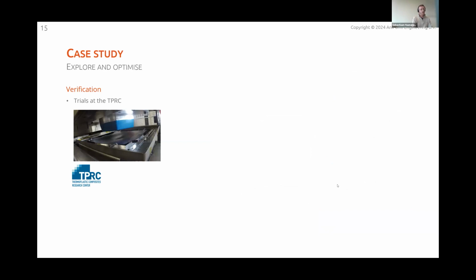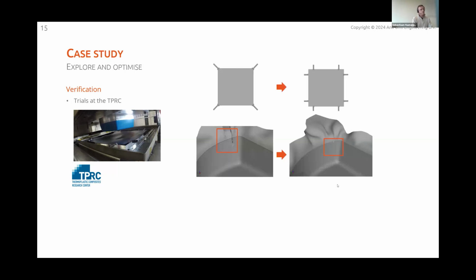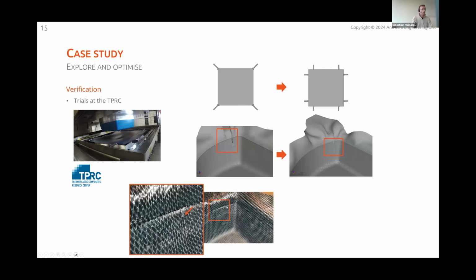Of course, we can do some verifications. We're a member of the TPRC, so we have access to the press over there. So we did a lot of trials in the past, and well, this was the situation, like you remember. So tensioning like this and tensioning like this. And we did that in practice as well. And if we zoom in on the part, if you look carefully, you see that the fiber directions here take quite a different direction. The wrinkle is not that obvious, but from this discontinuity here, you can actually conclude there was a big wrinkle in there, but now masked away a bit by the huge pressure that was exerted on this part.